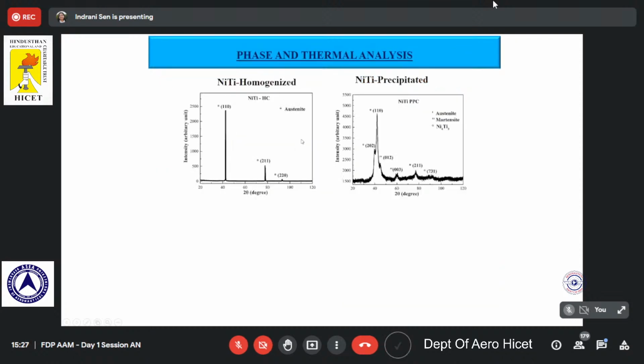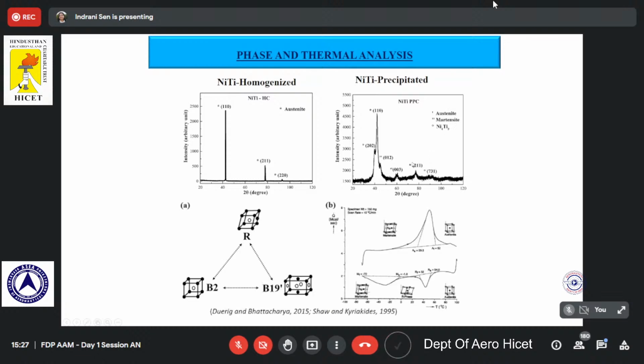Okay, when we did the XRD, unlike the homogenized one, which is made of fully austenite structure, in this case we find the existence of not only martensite but also precipitate in the XRD itself. So even if we are not visualizing it, we are able to find out the martensite and the Ni4Ti3 precipitates right from the XRD itself. Okay, fine. So now the structure has been changed.